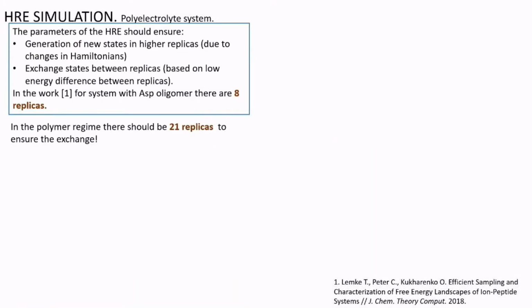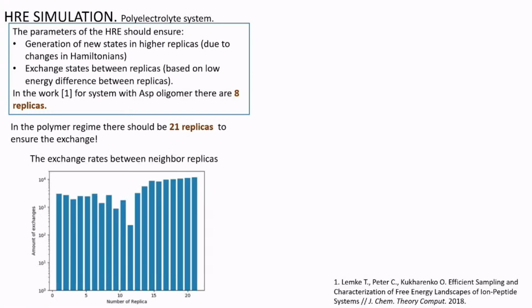But anyway, it was an oligomer. In our case, we obtained exchange between replicas using 21 replicas. We think it's because of the polymer regime, it has a lot of salt bridges, and the restrictions in this case are much higher.